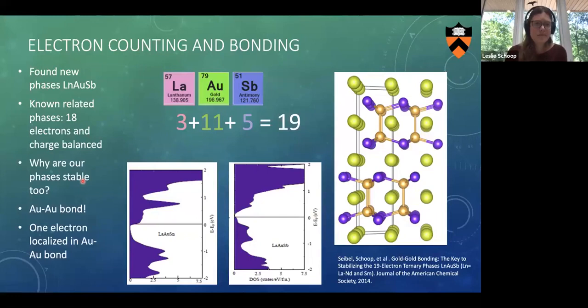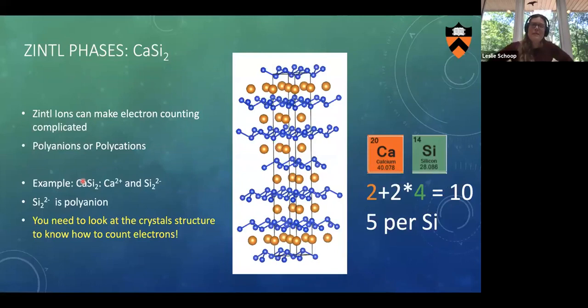Okay, so it is actually not that uncommon that something like this happens. This is a class of materials called Zintl phases. And the prototype, a textbook example of Zintl phases, is calcium disilicide. So let's look at this material. So here's the crystal structure. If you would count electrons in calcium disilicide, you would count two per calcium, and then four per silicon, and you got this twice, which makes 10 electrons in the total formula unit.